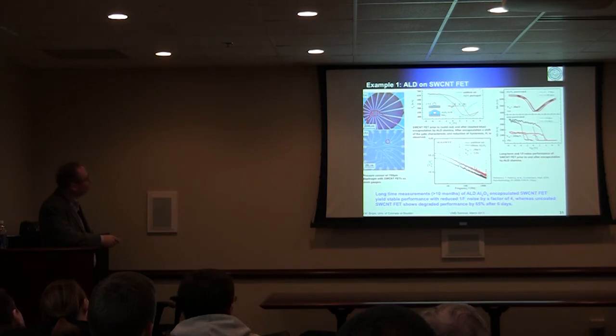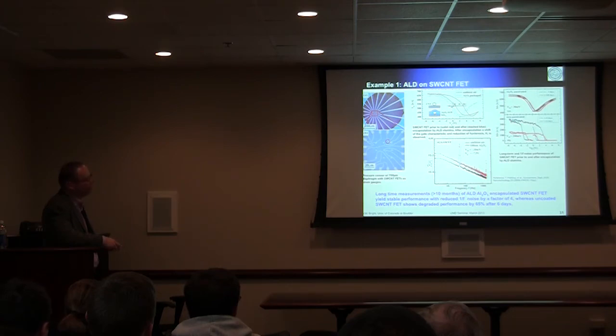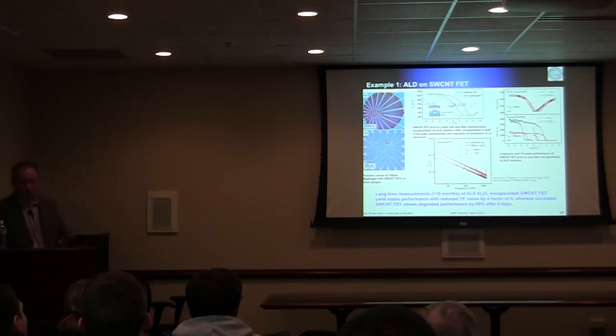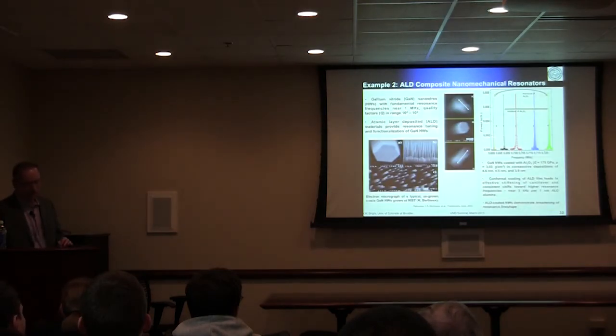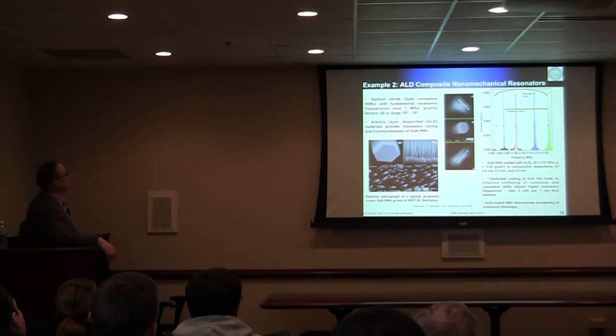Now, if you coat the contacts with ALD, you stop oxygen diffusion or moisture into the contact. And so what happens now, the red curve is after 100 days. And so the device actually turns out to be much more stable over time. So maybe it's a technique for encapsulating nano-scale type of devices.